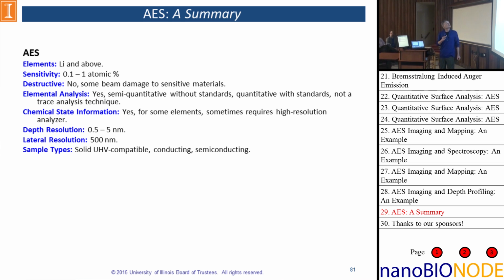With Auger, we're going to be able to see lithium and above. The one drawback of Auger is that to make the Auger process work, you have to start with at least 3 electrons. And lithium happens to be the first element that has 3 electrons. And so I want all you guys who can remember my Auger transition process, the physics behind the process, to try to figure out in your minds how we get an Auger electron out of lithium. It's not as easy as you think.